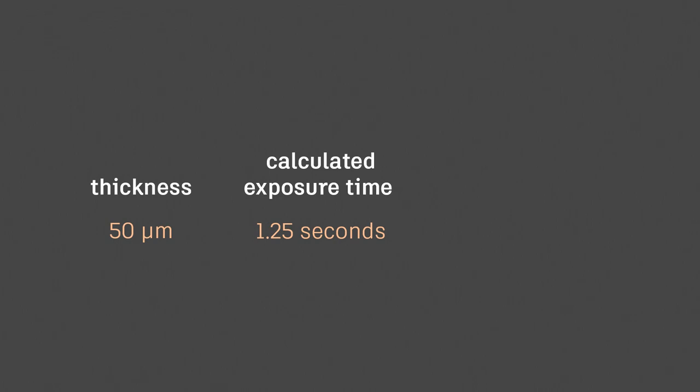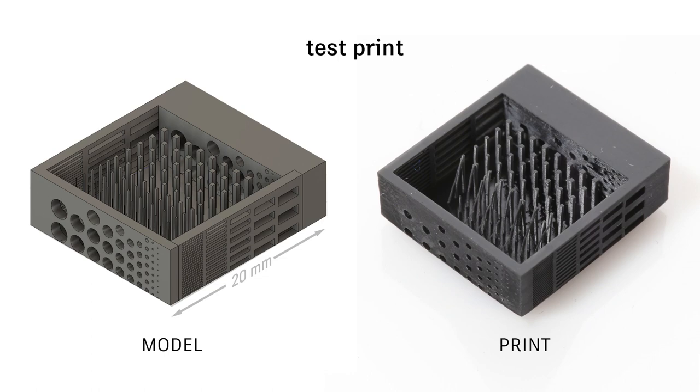In practice, for the layer to fully adhere to the previous layer, the exposure time is usually between 20 and 40% more time than is specified on the graph. You can figure this out with a handful of test prints.